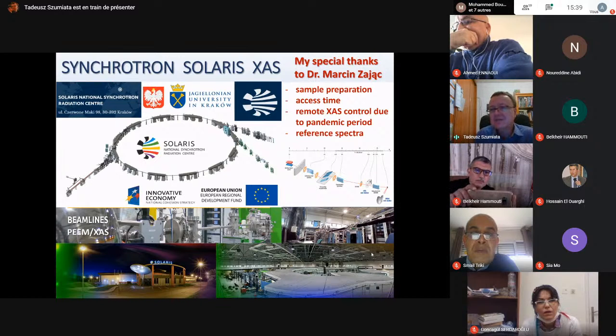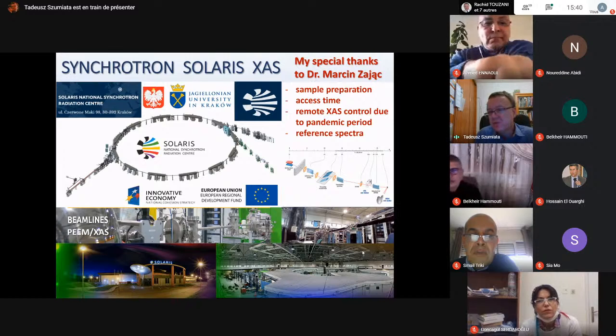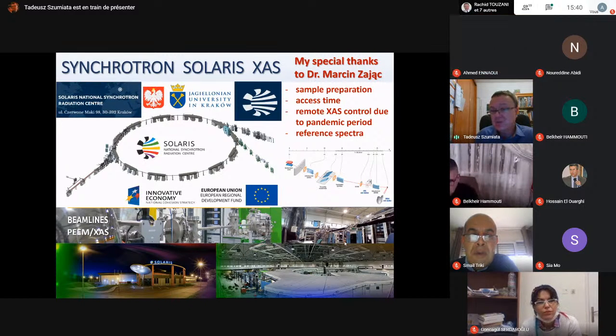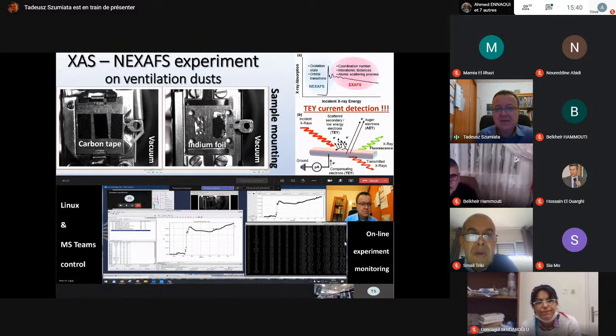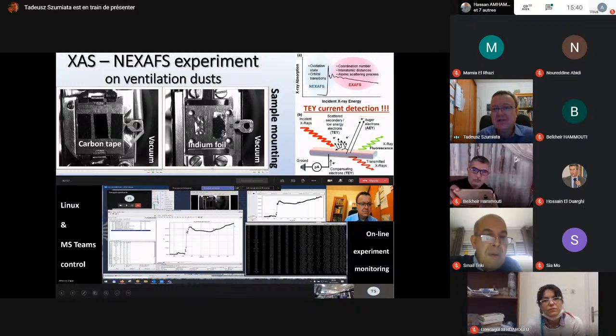Many thanks, special thanks to Dr. Marcin Zając for the sample preparation and for giving me a nice opportunity for remote control of such huge experiment from my home in this difficult pandemic period. Here you can see some details concerning the mounting of the samples on the carbon tape or indium foil, and also some ideas concerning a very special method of detection, this total electron yield mode, very effective, very sensitive. Okay, and what are the results?